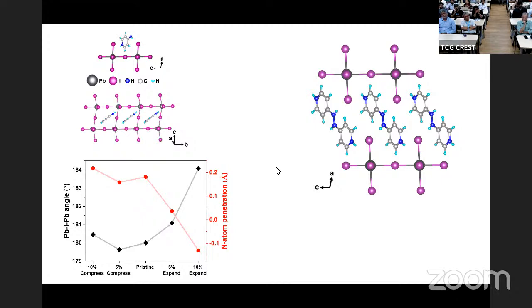So we ask the question, how much can I push it in? Can I push in further? This was realized by calculation, by varying in the c-axis the dimension and allowing the AB plane to adapt for energy minimization, and that is shown over here. This is the actual distance that the system wants to be in, which is the lowest energy. You can expand it or you contract it. When you contract it, you are trying to push the head inside. When expanding it, you are trying to take the head out. This is how much the N atom penetrates below this layer. When it is expanded, it is above the iodine layer by this much.